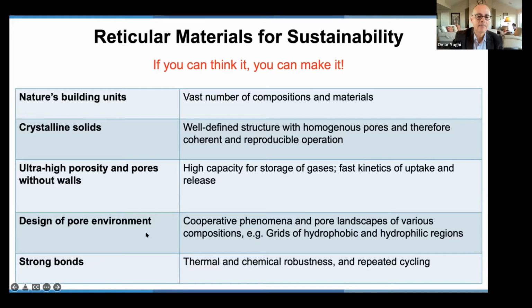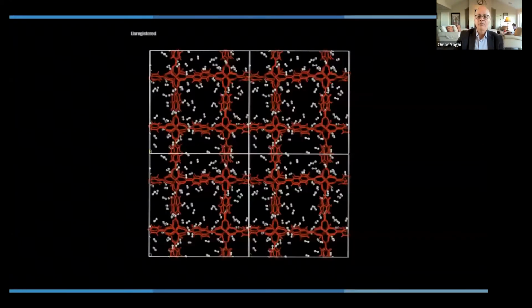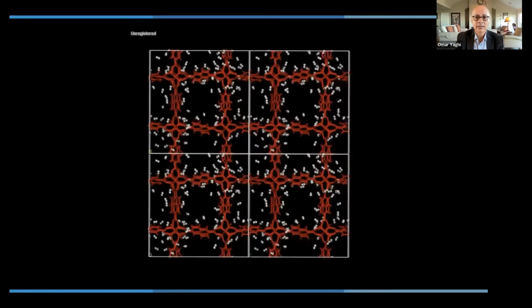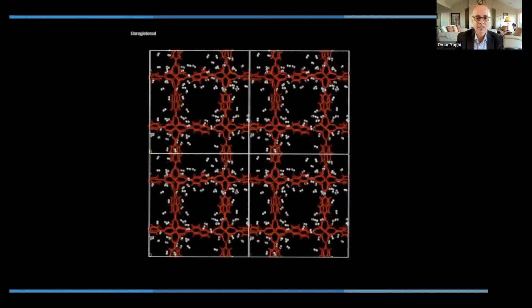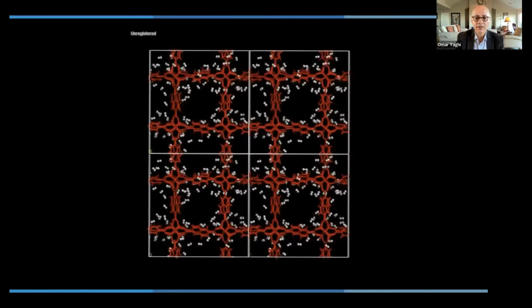throughput of the system. Design of the pore environment is that if you can craft the interior of these materials so that you can have cooperative phenomena like oxygen binding, let's say, to hemoglobin, the same kind of phenomena is observed in the water harvesting systems. And I'll show that shortly. Strong bonds, I've already mentioned, give you the thermal and chemical robustness that you need for repeated cycling. So for hydrogen storage, the idea is to make systems, let's say a MOF, as you see here in red, that can take up hydrogen, and the hydrogen is interacting with the framework.